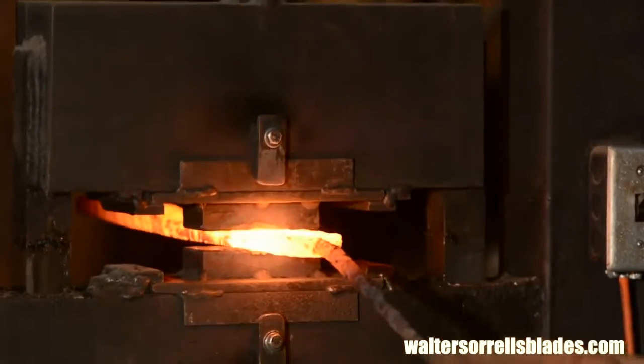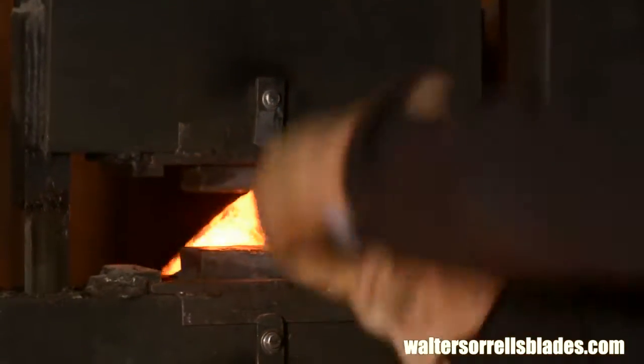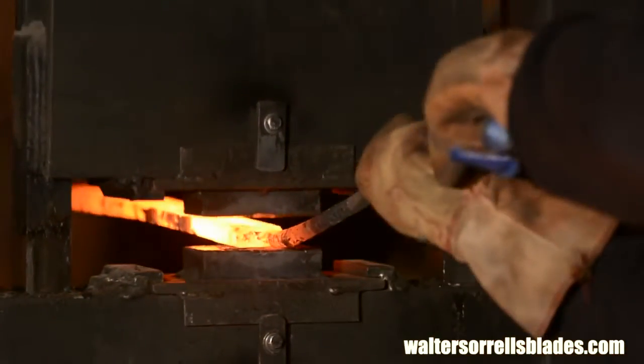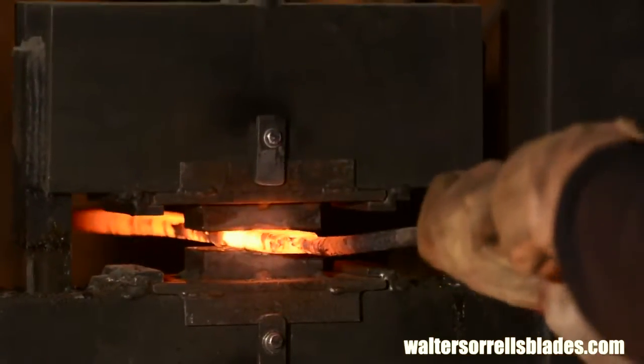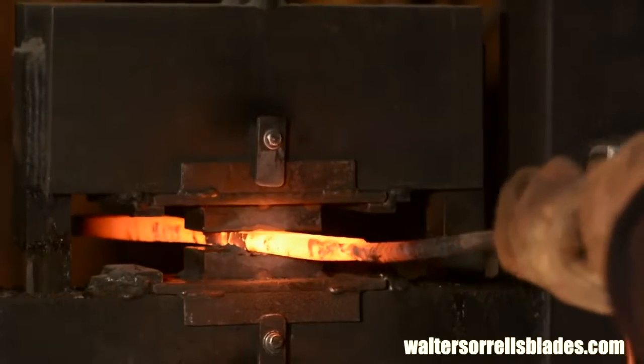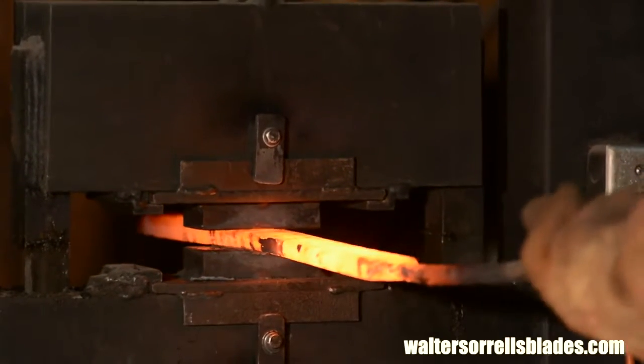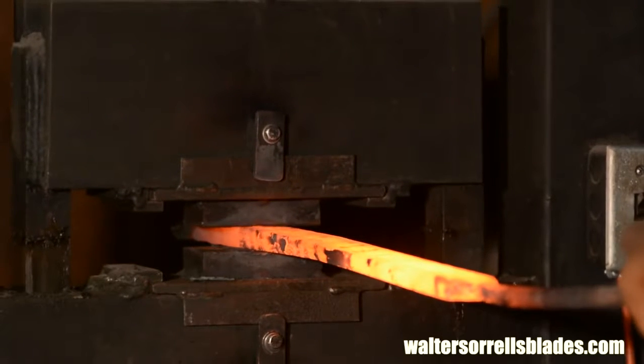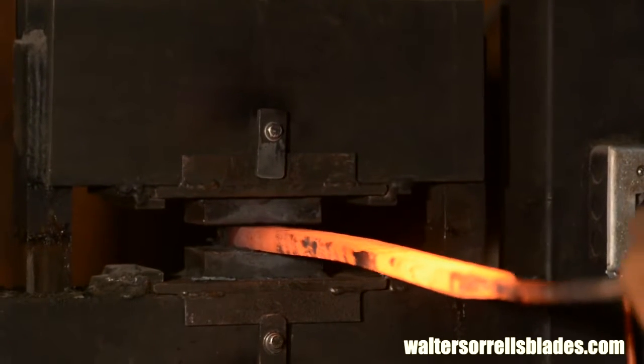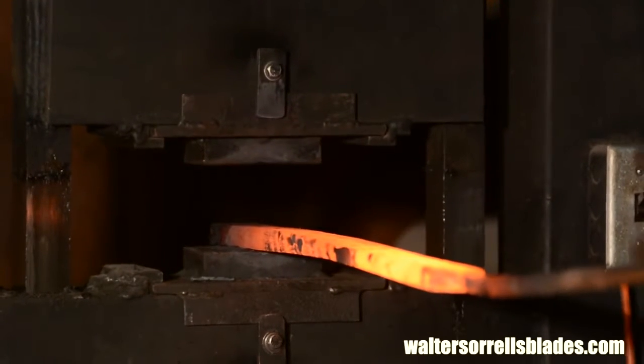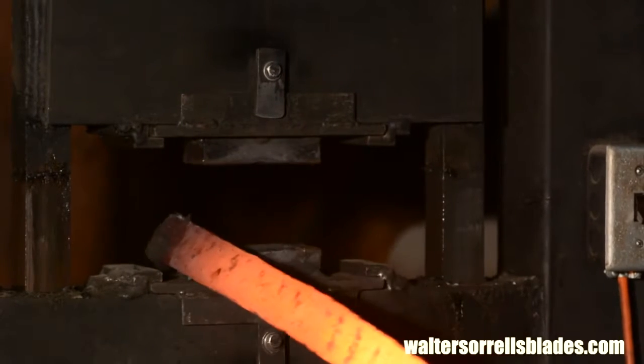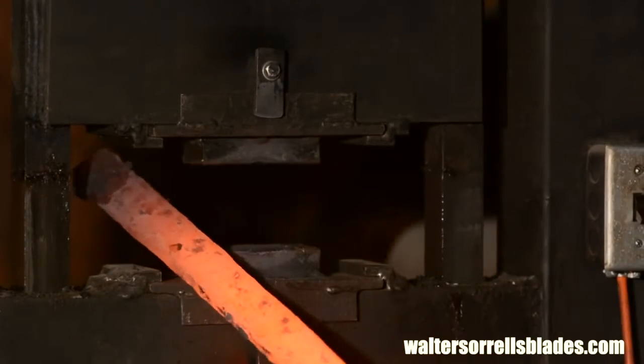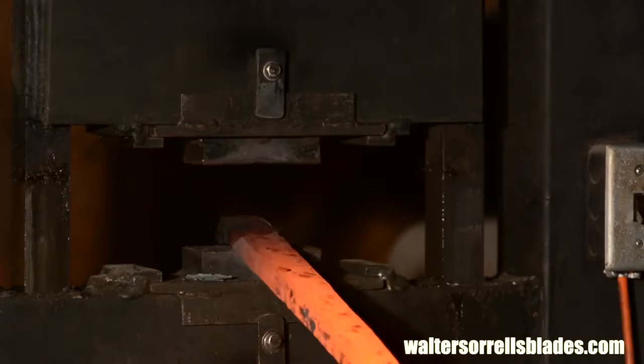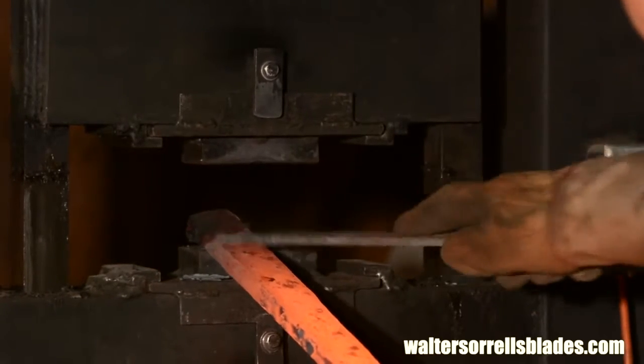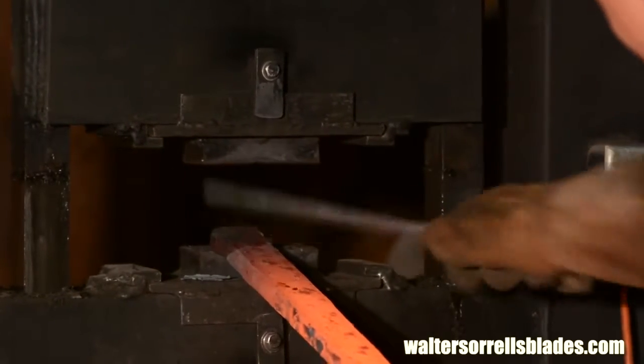One thing you'll note as the blade gets longer is that you can't heat the whole thing in your forge, so you have to work it in sections. This will be totally dependent on the nature of your forge. Depending on what you're doing, you may quit after the first pass, but we'll be doing what's known as random pattern Damascus, which requires a fair number of layers to result in an interesting pattern, so we need to build up more layers.